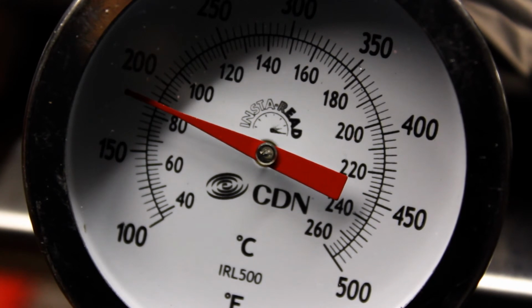Once the Parkerizing solution has reached temperature, you can add your parts. Many prefer to preheat the parts close to temperature by immersing the parts in a hot water bath. I have tried both preheating and just placing the parts directly in the solution. I personally saw no difference, but that doesn't mean one doesn't exist on the microscopic scale. Once the parts are in, they will begin to emit small bubbles. Parts should sit in the solution for about 15 minutes and then be placed into a running water bath. A light scrubbing with a soft brush helps remove any stubborn phosphate residue.